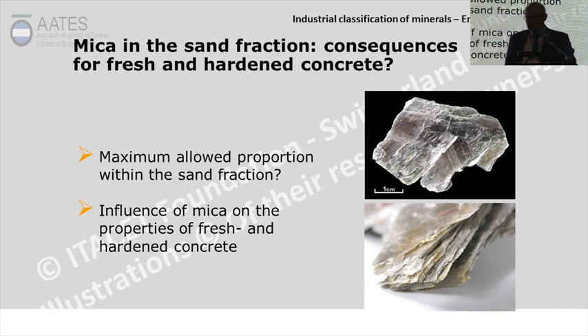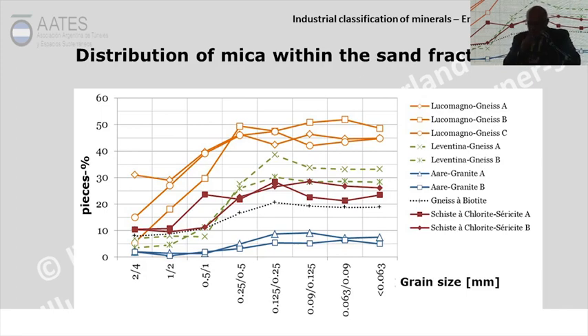One of the hard points is mica, because mica often avoids that we can use the material for concrete, because it brings the strength down. But mica is not mica, and that's why the regulation of the European Union is good to standardize the test. You see here a chart of the mica content of different lithologies from the Gotthard base tunnel. And you see that the mica content depends on the grain size where I measure the mica. If I measure the mica content in a grain size, let's say between 1 and 2 millimeters, I have almost nothing. But if I measure the mica content in the fine-grained material, the mica goes up, because the mica collects in the fine-grained fraction.